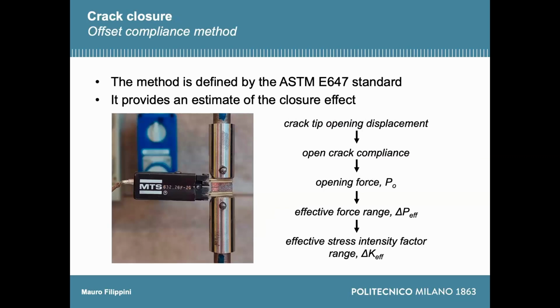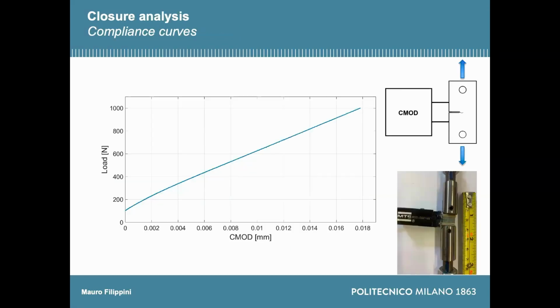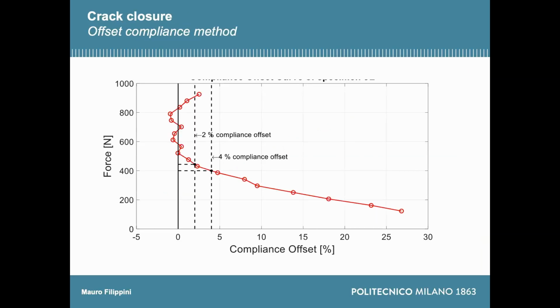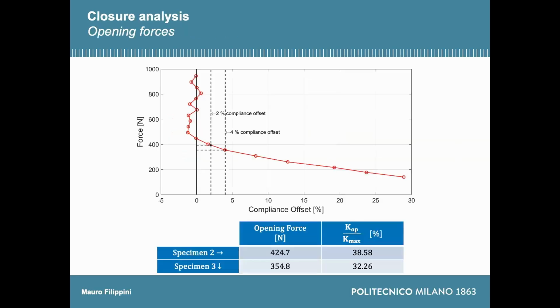Okay, so we needed to highlight how much crack closure we had for this growing crack. And so we did the test according to the ASTM, even though we had this unconventional sub-size specimen. And we used the offset compliance method to measure the crack closure level. And this is quite standard, so I will not go into details unless you ask questions. And we could measure a level of opening, which is about 35% with respect to the Kmax. So you have a definite crack closure effect,